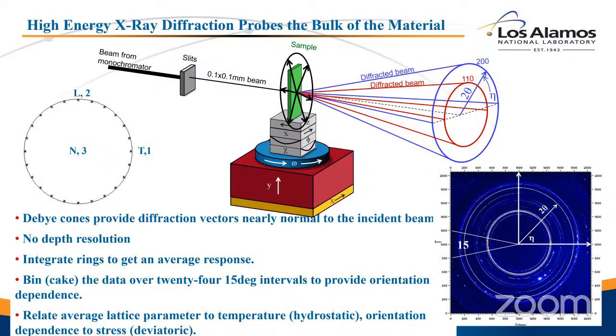So this is actually the Debye-Scherrer cones that I referred to here. We measure about 5 different Debye-Scherrer cones for each phase that's in the austenite, or I'm sorry, in the stainless steel. So the austenite, the ferrite, we'll see 5 different HKLs, 5 different peaks from each phase. And that gives us enough information to determine phase fraction and separate phase fraction from texture and things like that, and Debye-Waller factor to a degree.